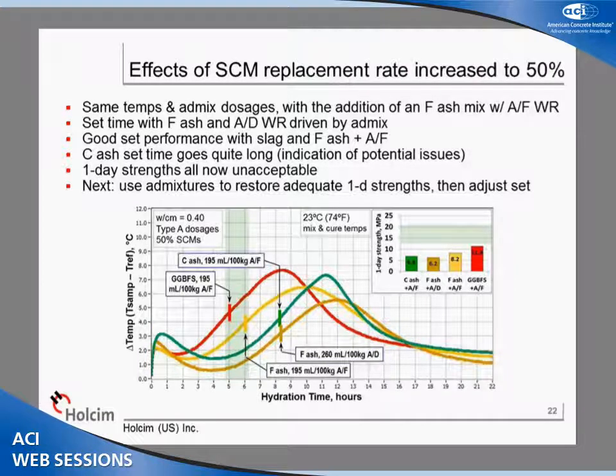It's interesting as a next step to see just what might happen if we do nothing but go up from the 15 or 30% cement replacement to a 50% cement replacement. If our specifications are calling for a concrete mix that has only 50% ordinary Portland cement content, then this would be an interesting next step. And of course, we see some mixtures with some retardation effects. We see much lower one-day strengths. We're going to have to adjust the mix proportions to account for those things.